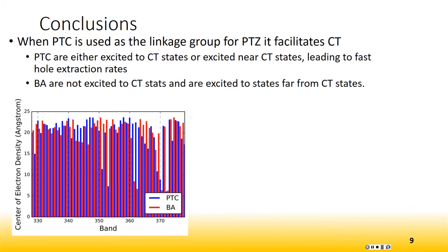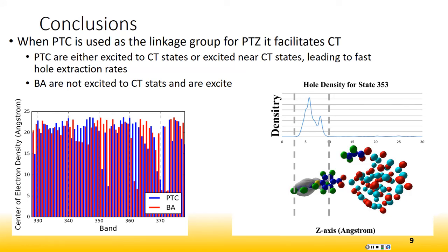So in conclusion, we can conclude that PTC facilitates charge transfer because it is either initially excited to a charge transfer state or it is very close to a charge transfer state, where BA has to relax down to a charge transfer state, which will increase our rate for hole extraction.